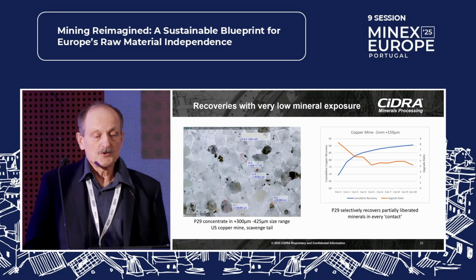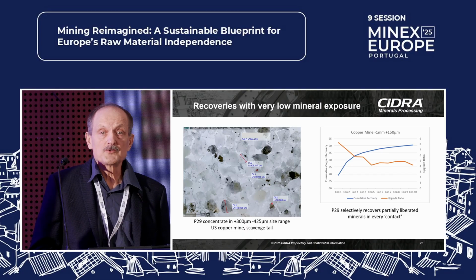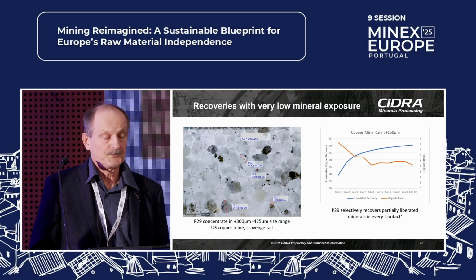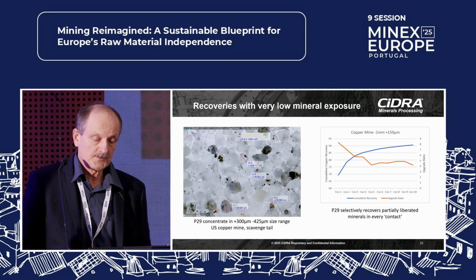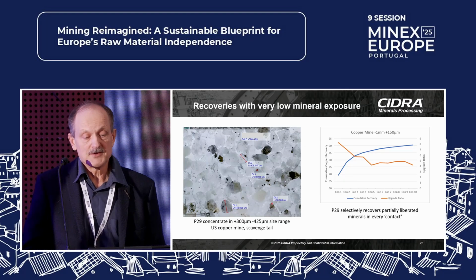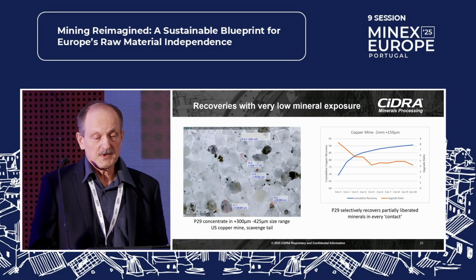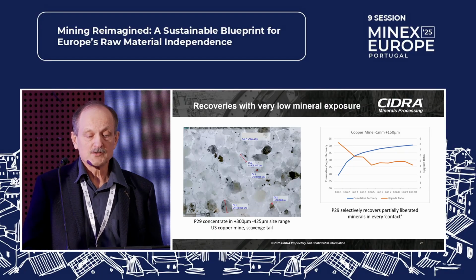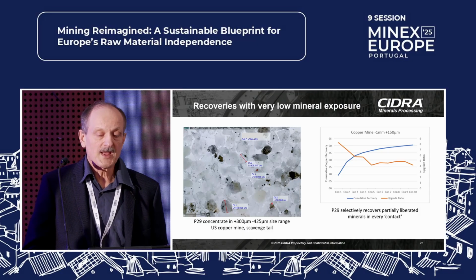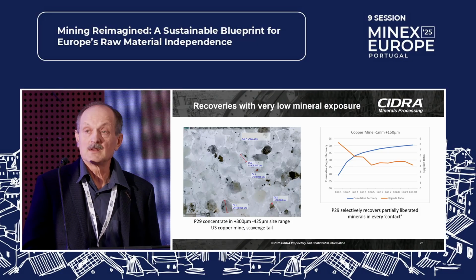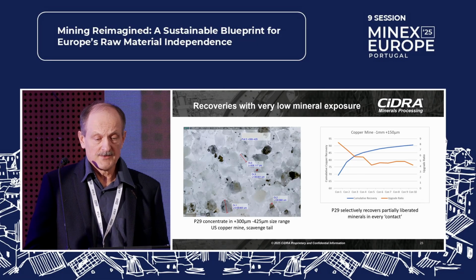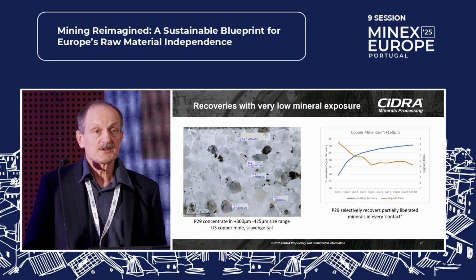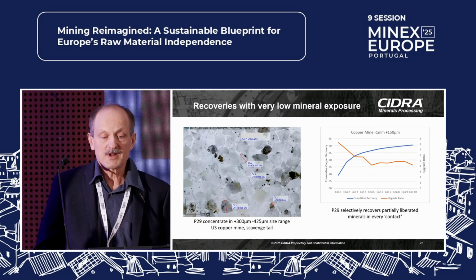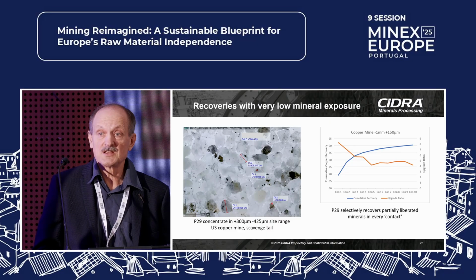The drums we call contactors, so you can put a row of those and control the wanted recovery to whatever level you want by increasing the number of contactors. Here we can see the example of 9 contactor rows, and you can see that still in the last one, the upgrade ratio of the material is more than 4, so there's 4 times more of the valuable materials in the concentrate than in the feed of the last stage.